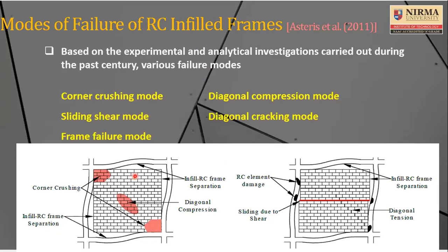But most importantly, while carrying out all such experimentation, we could figure out, as an outcome of that experimentation, that there are different types of failure that we are able to observe in reinforced concrete infill panels. Some of them are listed here, and these are very common types of failure observed through experimental investigation, and because we have observed them experimentally, now we are able to analytically capture them through computer modeling. Until we carried out this experimental investigation, we could never have understood what kind of behavior or failure this masonry infill undergoes under lateral loading, and because of that now we are able to model it with a single diagonal strut or multiple diagonal struts.